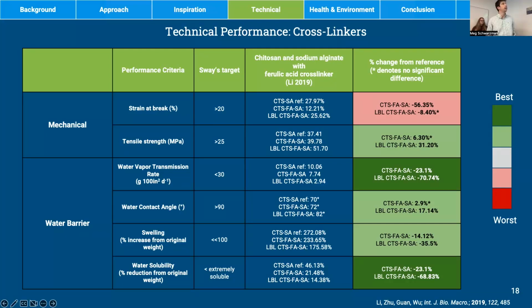If we compare it to the baseline reference, we can see that there is an improvement in our water barrier metrics that once again can be associated to a denser structure. Ferulic acid, and cross-linkers in general, act to create a denser structure as they draw together the polymer chains. In this case, we can visualize that ferulic acid can cross-link these two polymers via hydrogen bonding with sodium alginate and electrostatic interactions with the chitosan, hence our inclusion of chitosan in this suggestion.